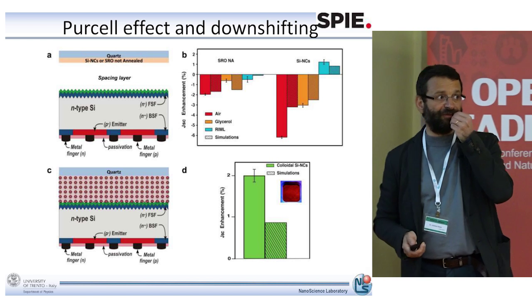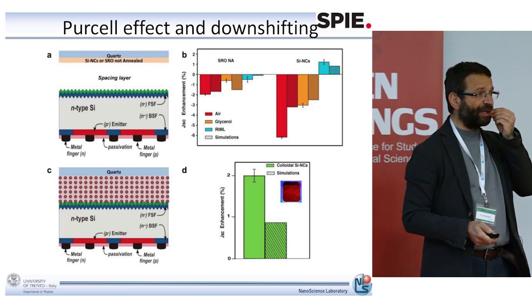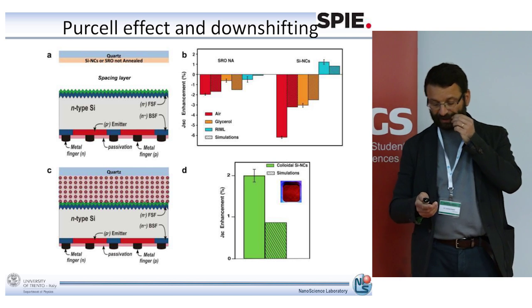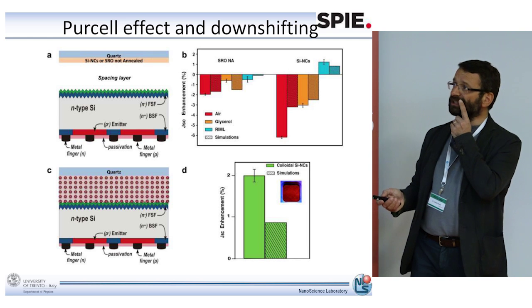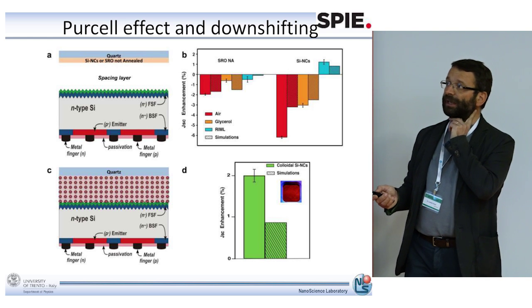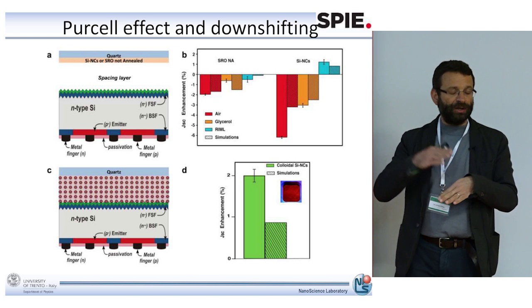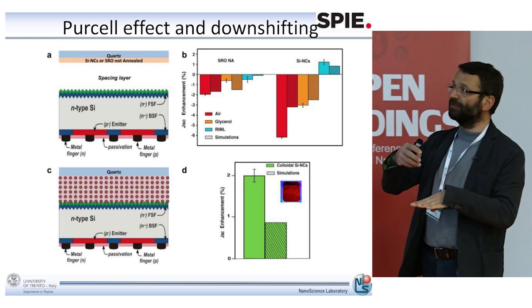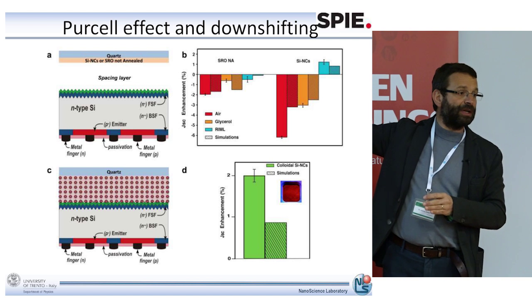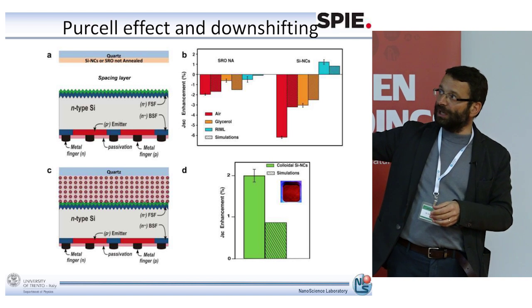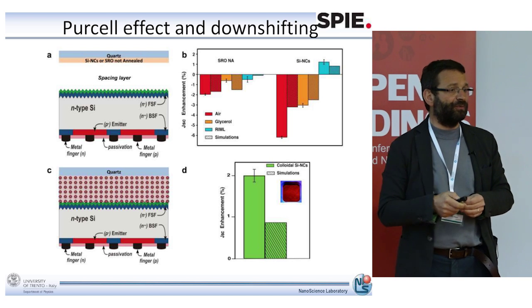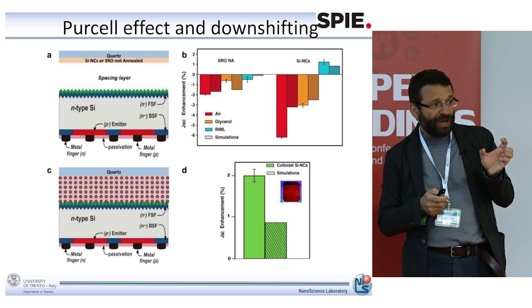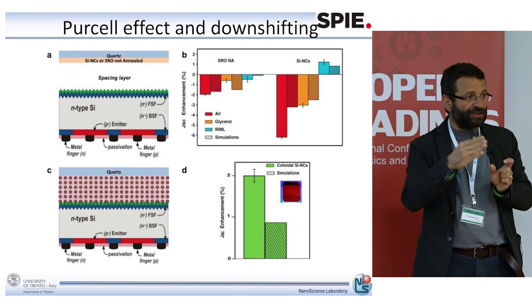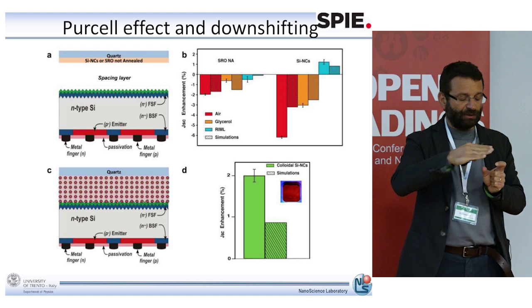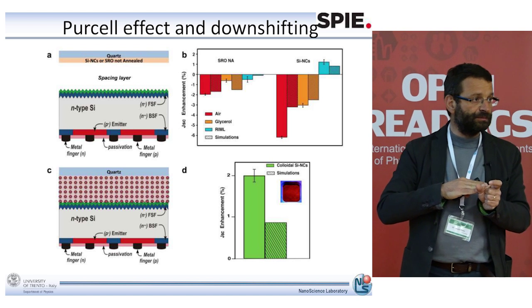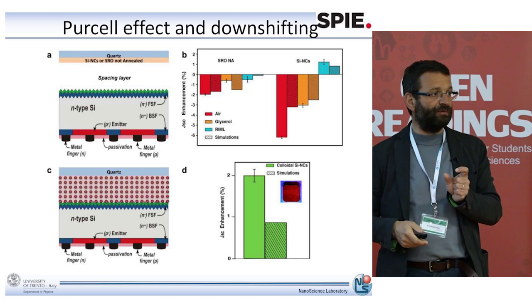However, we were puzzled by the fact that the nanocrystals could affect the interface quality of the cell. So we repeated an experiment. We did another experiment where the nanocrystals are not placed on top of the cell, but are placed on a covered quartz plate that we put on top of the cell. So we physically separate the nanocrystals from the cell. In this way, in all the experiments, we use the very same solar cell. We aim to see whether the effect is simply due to the nanocrystals passivating the cell better or not. We separate them, so there is no longer a passivation effect on the cell.